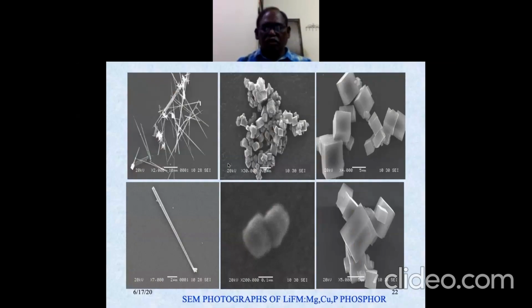In this material also, by changing the concentration of the ingredients or the starting materials, by adjusting the pH of the solution and the amount of ethanol that we have used, one can also change the morphology, because we had to see whether the morphology has some effect on the luminescence properties of this material. Here you can see that we could synthesize these long nanorod or needle-shaped particles. Then by changing some parameters, we could also prepare this in cubic or particle form. And by the same technique, we could also prepare microcrystalline material.